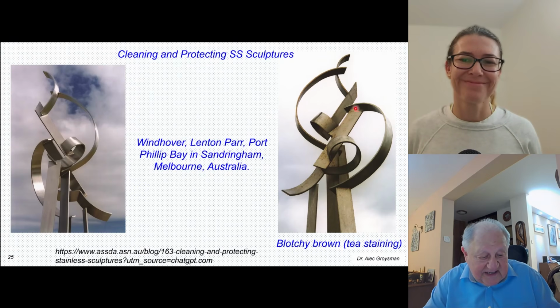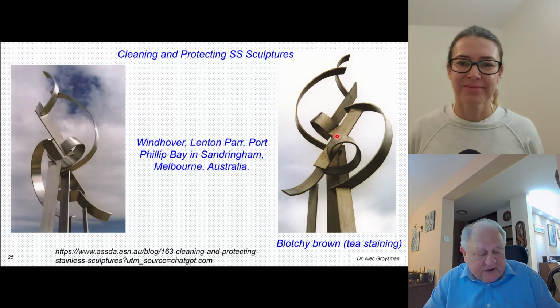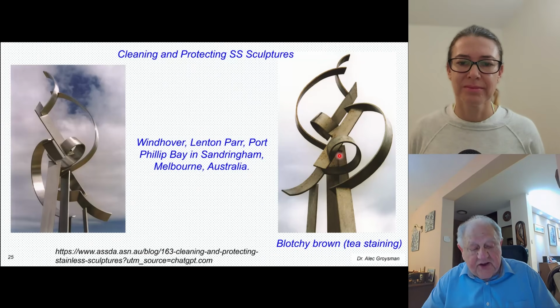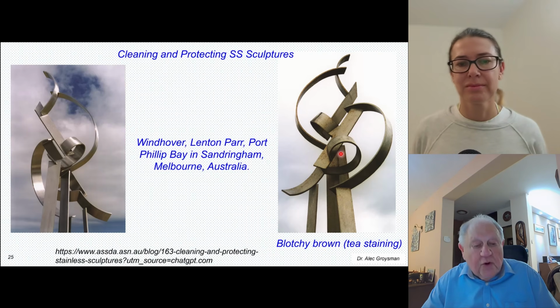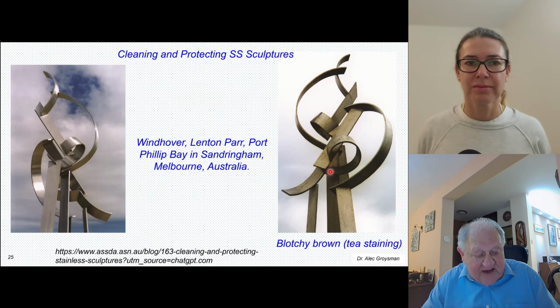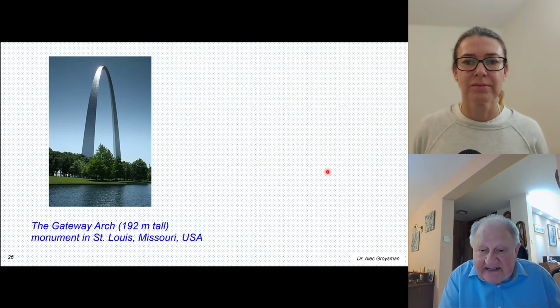You may see brown tea staining. It's caused by deposition of salts on the surface, which were trapped in the crevices of the brushed finish. Regular reactivation by rain has perpetuated a corrosion cycle, leading to quite rapid and severe surface staining.